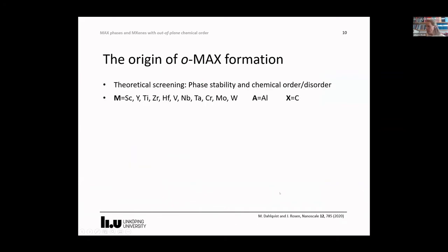The first new study that I will present today, let's see where I am time-wise, is a theoretical study where we have looked into the origin of o-MAX formation. So we have performed a theoretical screening of the phase stability and of chemical order and disorder of the o-MAX phases. We've used these M elements. We have looked at aluminium, since aluminium is prone to be etched and form a MXene, and we've used X equal to carbon.